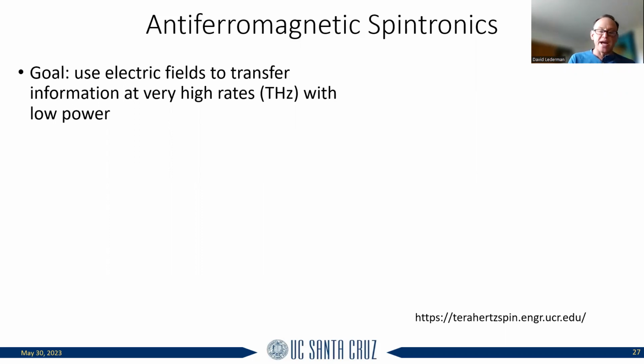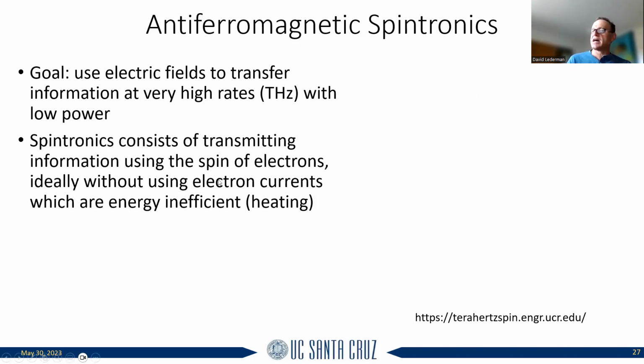When you use a ferromagnet, the characteristic frequencies are usually in the gigahertz. So this would give you a 1,000 times increase in speed. And just as a reminder, spintronics consists of transmitting information using the spin of the electrons. Ideally, you want to avoid having charge currents, right? Because that's where you get most of the dissipation of energy. And so if you want to make a low power electronic device, then you want to have a pure spin current, where you have some sort of magnetic signal that travels, but you still have the problem that you have to somehow get an electrical signal out of that, because that's how we use electronics, right?